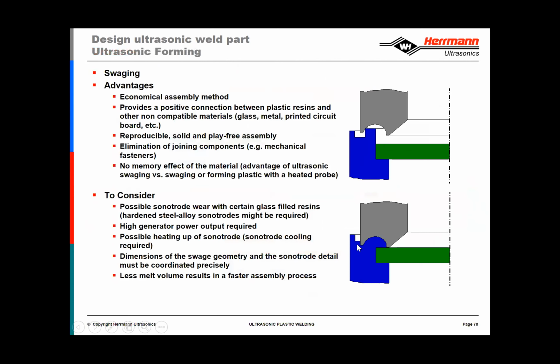Another consideration is that certain glass-filled resins, I mentioned earlier that glass is abrasive, can lead to wear. So having this glass-filled material in direct contact with the sonotrode very often results in wear of the sonotrode. Wear of the sonotrode then results in a larger volume. So therefore, you may not get as tight of a swage as you would have experienced previously or earlier in the production process. So it's something that has to be considered.